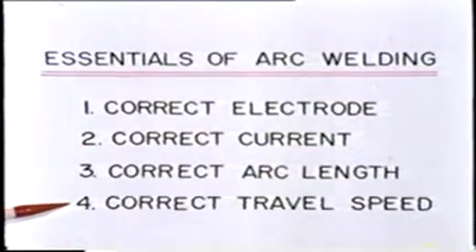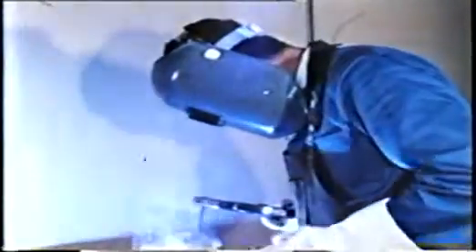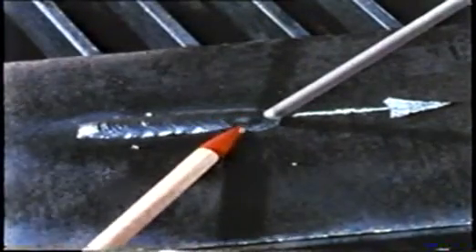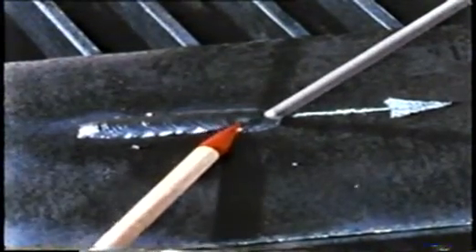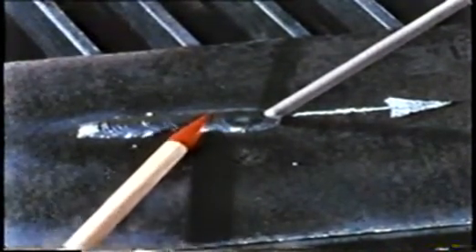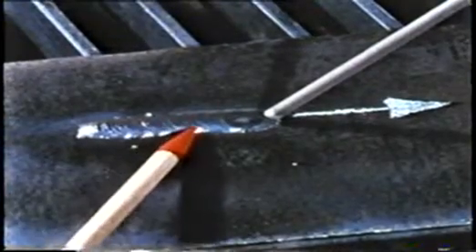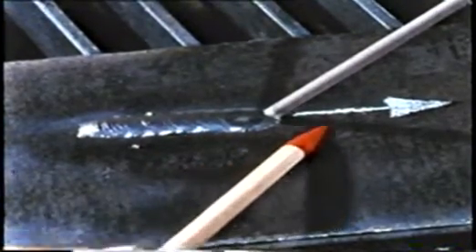Correct travel speed. The welder should attempt to produce 1 inch of bead for every inch of electrode used. Most beginning welders travel too fast. When possible, use your free hand to help steady the hand holding the electrode holder. A good welder will watch the molten crater, the finished bead solidifying directly behind the crater, as well as the path ahead of the bead during welding.